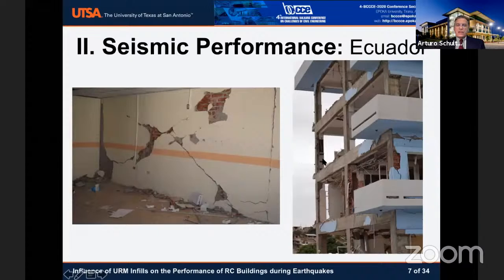On the right side, you see a four-story building. This was a hospital building, typical infill, in this case, clay and concrete, depending on which part of the hospital, and a reinforced concrete frame. The reinforced concrete frame was very, very well designed and built. There was hardly any damage to the concrete, but you can see that the damage to the infill is catastrophic, completely catastrophic. And so that's the kind of thing that you see again and again in countries that are susceptible to seismic movements and also have this type of construction.